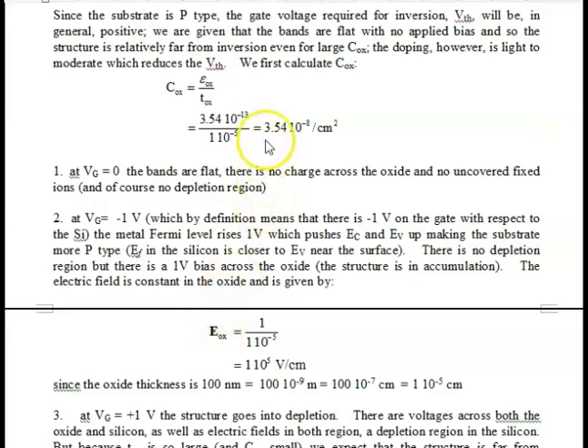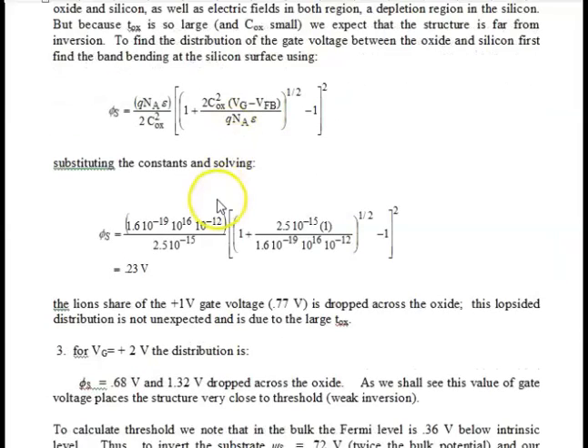And notice the oxide permittivity is less than the silicon permittivity, and the 2 times the gate oxide capacitance. Put in all this good stuff, and I get a silicon bending of about a quarter of a volt, and it bends down from neutral to surface. It bends down. Now I'm putting in +1 volt. Well, where's the other? I've only got 0.23 volts dropped across the silicon.